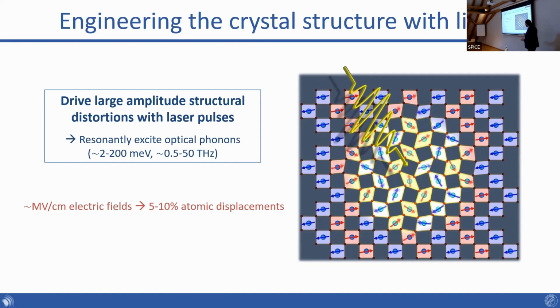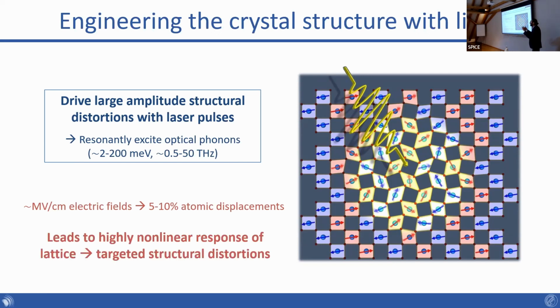And this will correspond, when you drive the vibrational modes, to atomic displacements on the order of a few percent of the equilibrium bond distances. And these are quite large displacements. And importantly, with these extreme atomic displacements, you enter a regime where the lattice starts to act highly nonlinearly. And you can actually take advantage of this to access specific crystal structures that you're interested in, which can lead to new functionalities, in this case, the magnetic properties that we want to control.